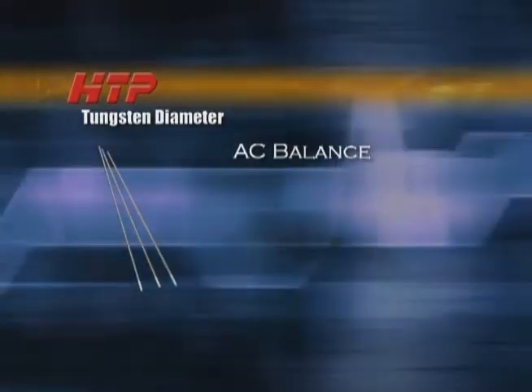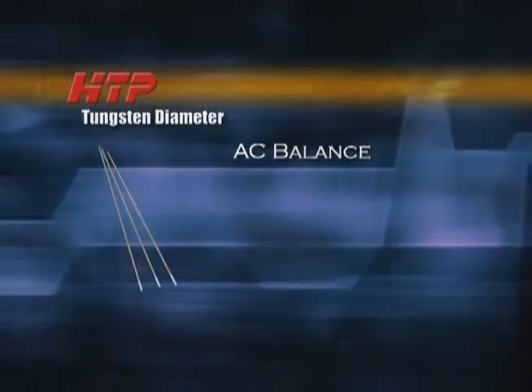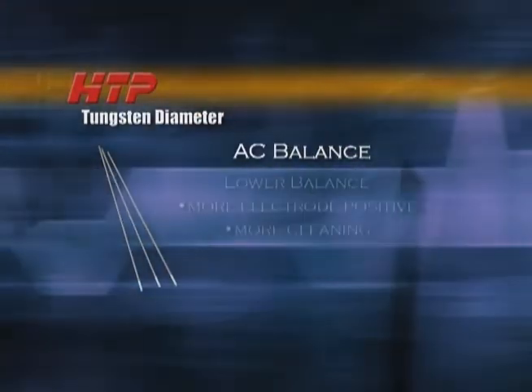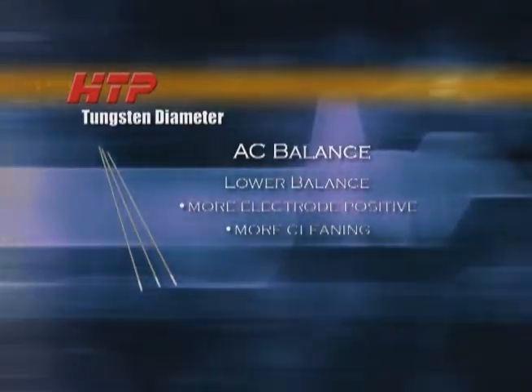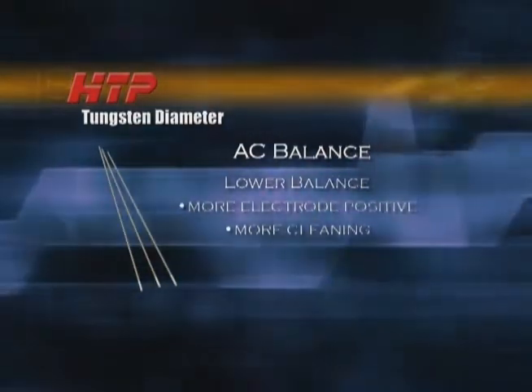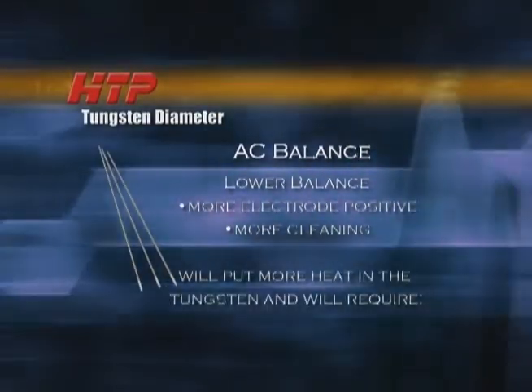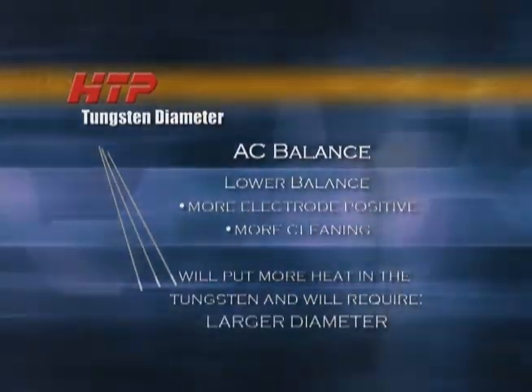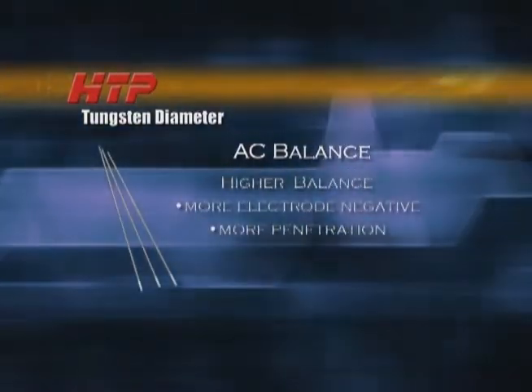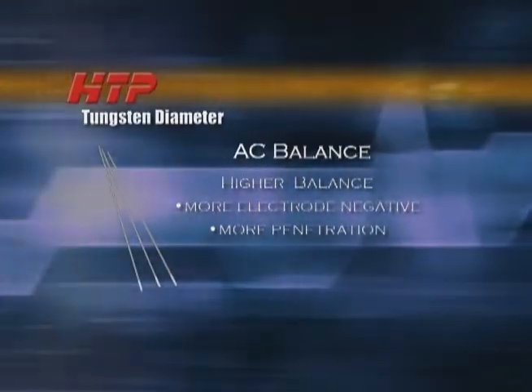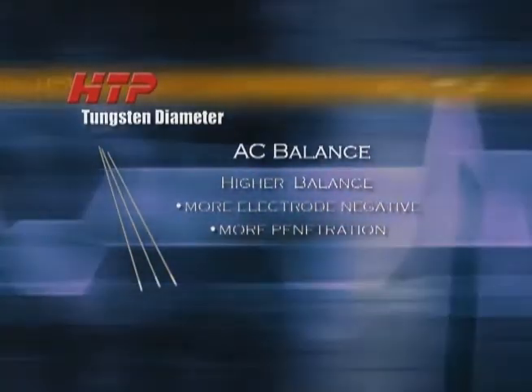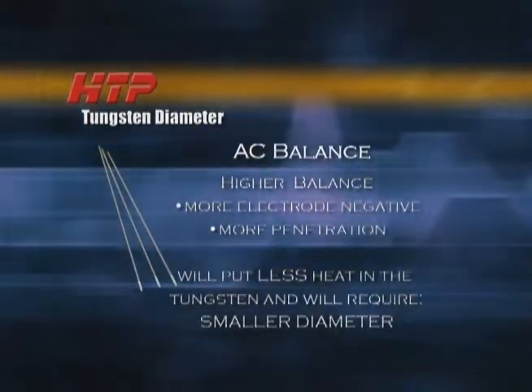Also remember that AC balance will have a great effect on the tungsten diameter which you select. A lower balance, more electrode positive, more cleaning, will put more heat in the tungsten and will require a larger diameter. A higher balance, more electrode negative, more penetration, will let you get away with a smaller diameter tungsten.